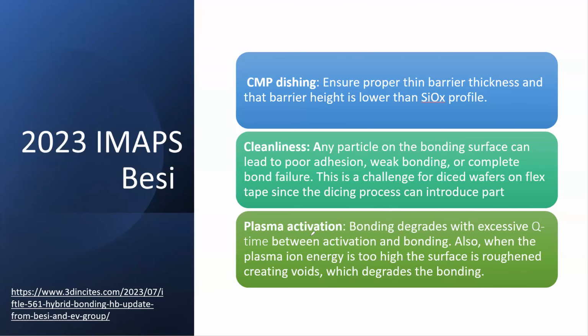But that plasma activation effect will degrade with excessive Q time. Q time means the time from the moment you finish the activation to the actual bonding, which could be minutes, could be seconds, I don't know. That time is called Q time. You queue up and wait. And if that Q time is too long, then the effectiveness of the plasma activation, where you put some chemicals, you do something to the surface, that effect is actually unstable. It's not a thermal equilibrium effect. And it will degrade as a function of time. If you have excessive Q time, then that defeats the purpose of activation.